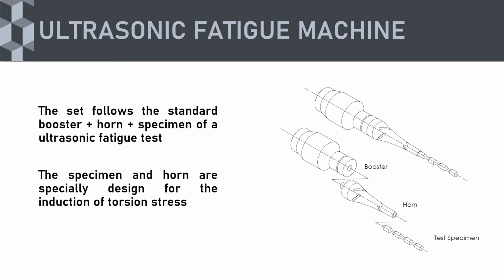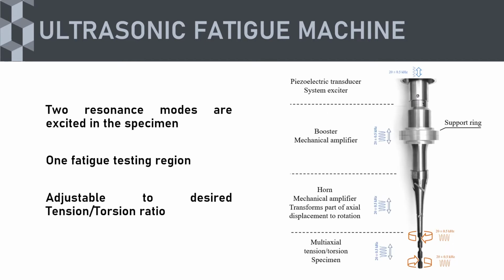Now, our machine follows the same concept of the basic tension compression ultrasonic fatigue machine. It follows the same booster, horn, and test specimen setup. The only difference is the specially designed horn and the specially designed specimen that are able to induce torsion simultaneously. The setup is able to induce simultaneously torsion to the tension compression because the specially designed horn induces a second resonant mode to the specimen. The setup is made so there is only one fatigue testing region where there is tension and torsion, and the specimen is adjustable so that we can have the tension-torsion ratio we desire.